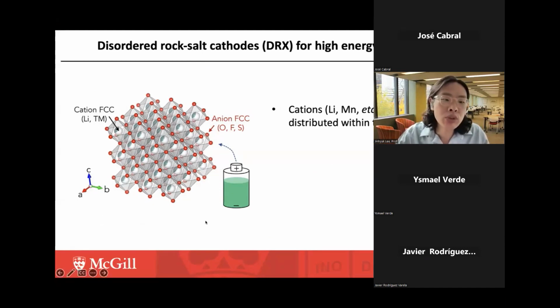Here I'm showing you the crystal structure of the DRX structure. In these materials, lithium and the transition metals are near randomly distributed within the cation FCC lattice, whereas the anions, such as oxygen, fluorine or sulfur, form the anion FCC lattice as well. You can consider these materials as brother materials of the layered rock salt cathode materials I discussed earlier, because they're both classified as rock salt crystalline materials. But unlike the layered rock salt, where there is clear ordering of the lithium and the transition metal, in this material lithium and the transition metals are randomly distributed. So we call this disordered rock salt.